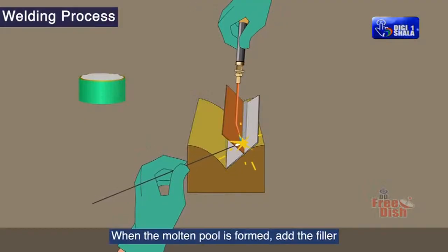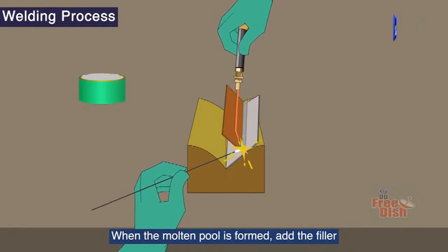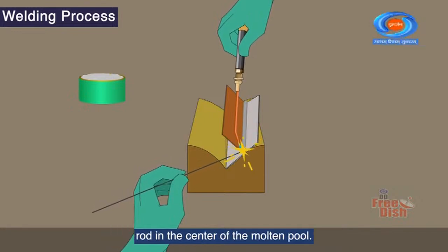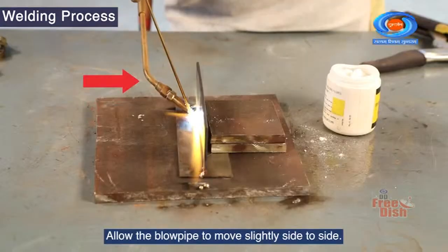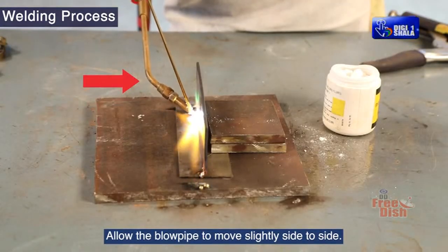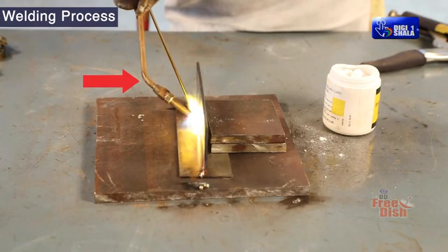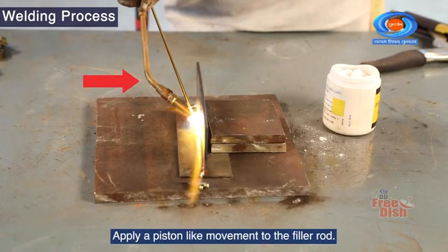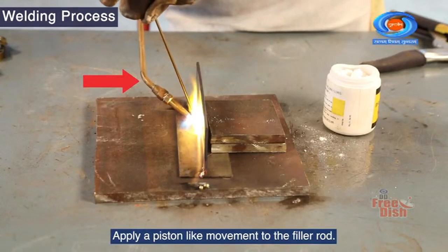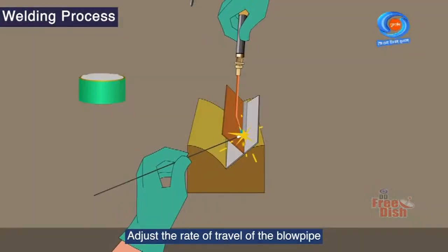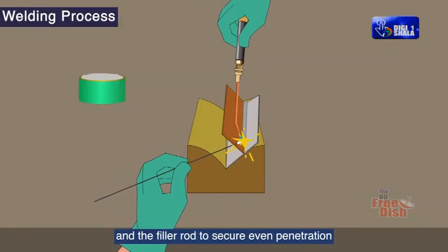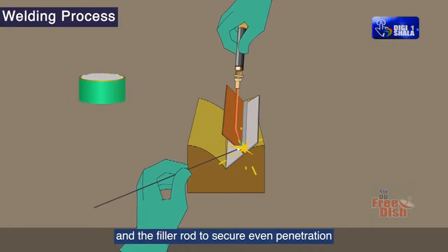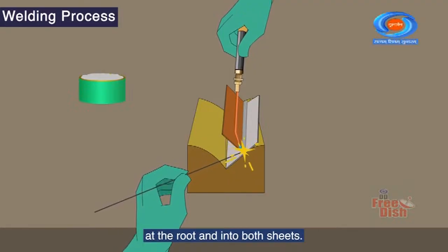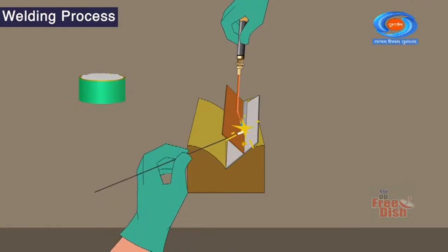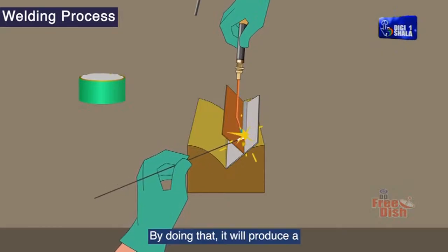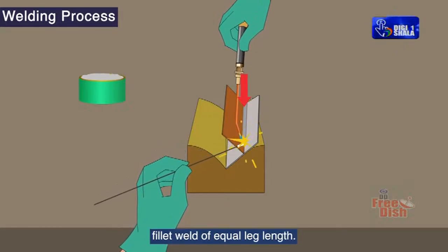When the molten pool is formed, add the filler rod in the center of the molten pool. Allow the blowpipe to move slightly side to side. Apply a piston-like movement to the filler rod. Adjust the rate of travel of the blowpipe and the filler rod to secure even penetration at the root and into both sheets. By doing that, it will produce a fillet weld of equal leg length.